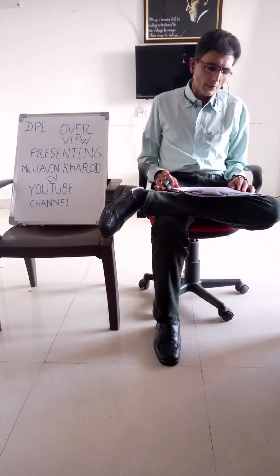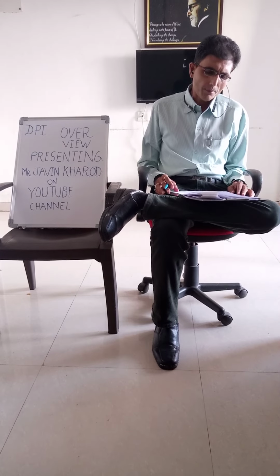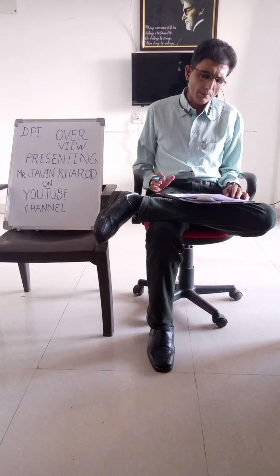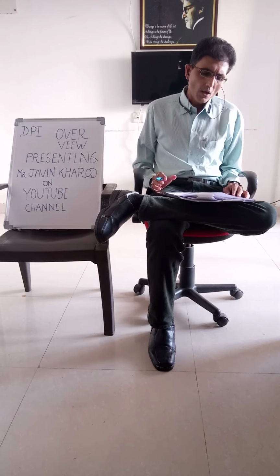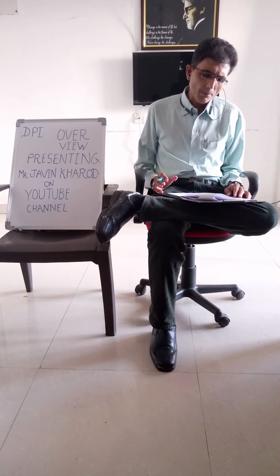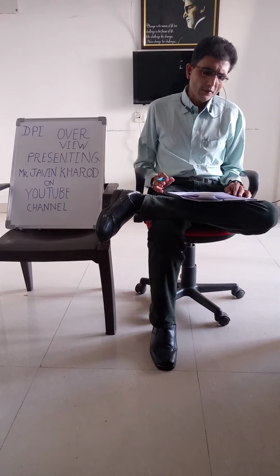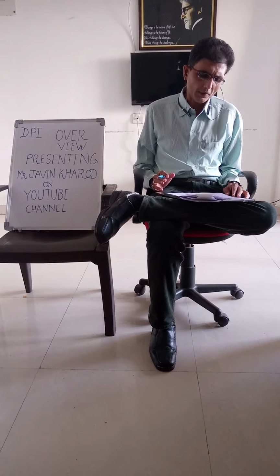Application of developer. After excess penetrant has been removed, a white developer is applied to the sample. Several developer types are available, including non-aqueous, dry powder, water suspendable and water soluble. Choice of developer is governed by penetrant compatibility: one can't use water soluble or suspendable developer with water washable penetrant, and by inspection conditions.